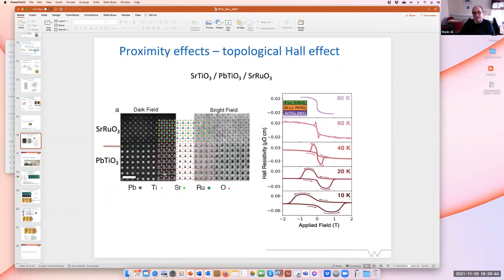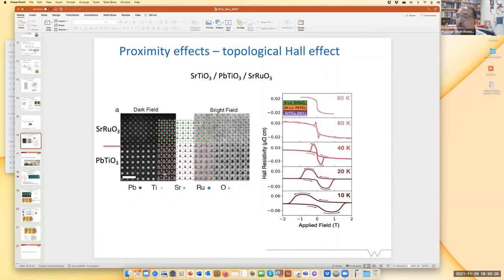Probably applying an electric field on them. Oh, that will do. Probably that will not move them. They will rather be destroyed. So in a sense, you orient polarization in one direction or in the other one, and then they can come back into a completely different pattern maybe, or something similar. I don't have this. There are some experiments run by the Ramesh group showing that there is an interesting interaction between light and those topological structures. And it is also interesting to see that applying an electric field destroys them. So that has been also done.